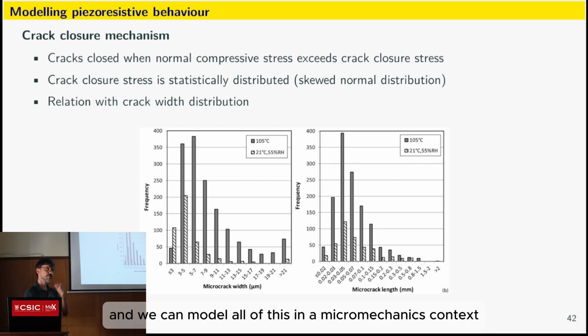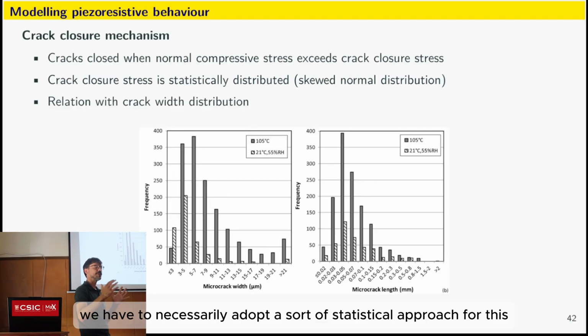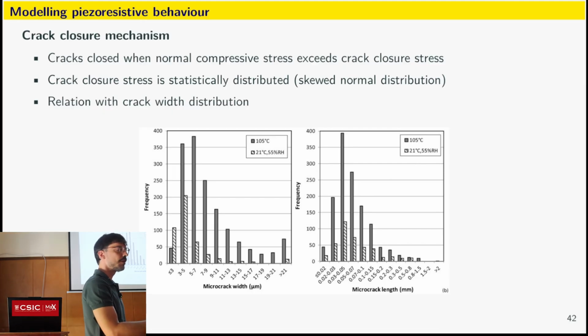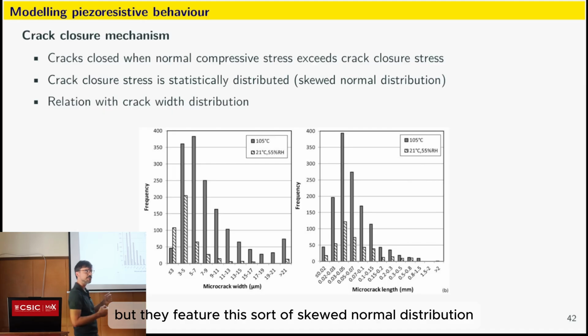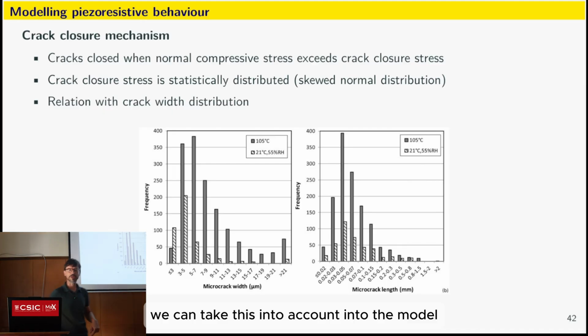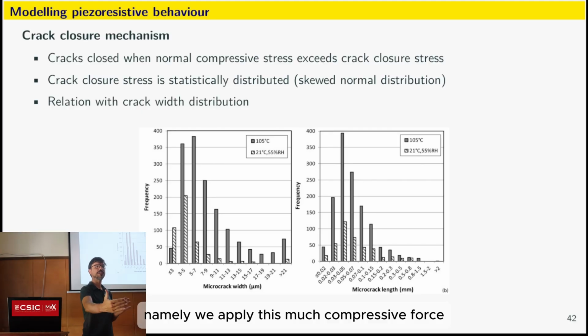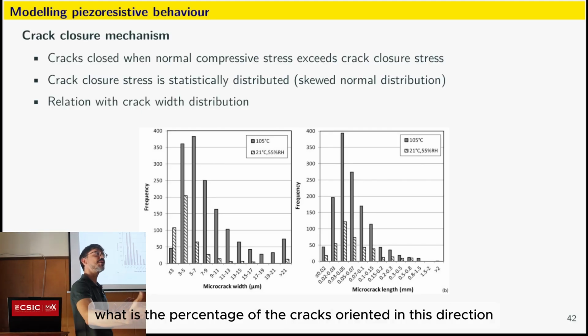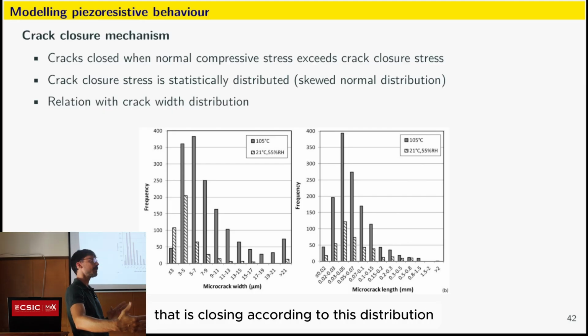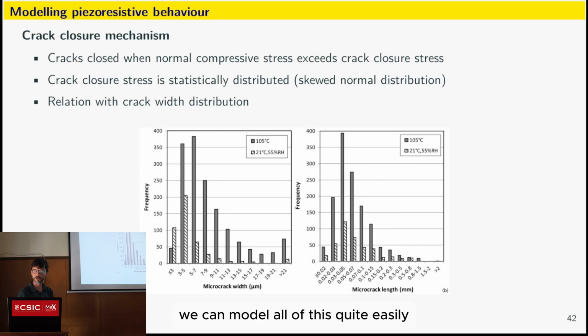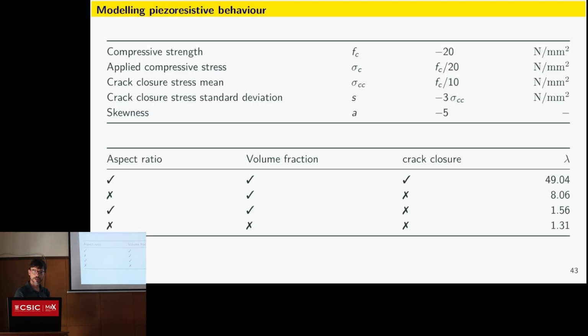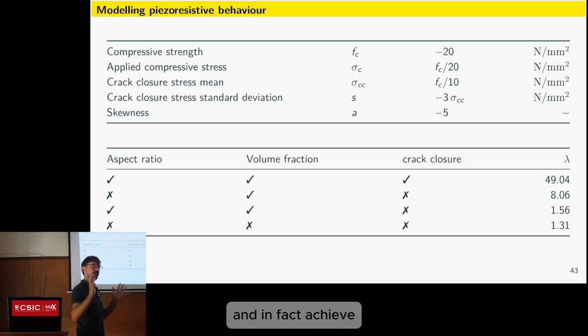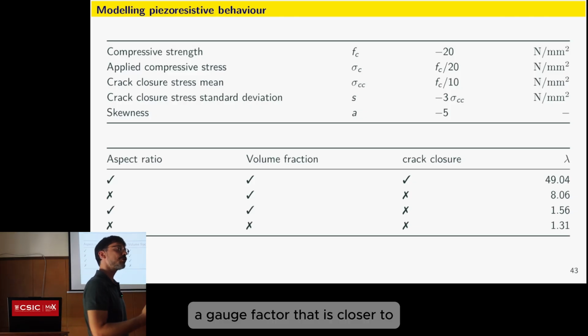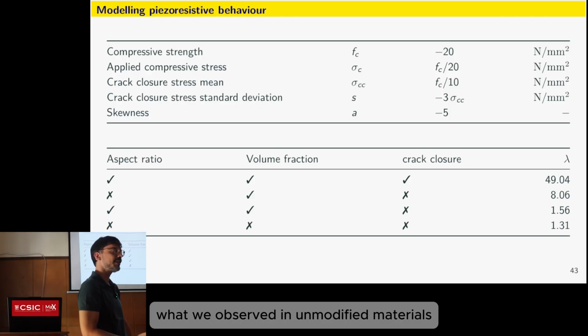And we can model all of this in a micromechanics context. We have to necessarily adopt a sort of statistical approach for this, because not all cracks have the same width, but they feature this sort of skewed normal distribution. We can take this into account in the model, namely we apply this much compressive force. What is the percentage of the cracks oriented in this direction that is closing, according to this distribution? We can model all of this quite easily, and in fact achieve a gauge factor that is closer to what we observed in unmodified materials.